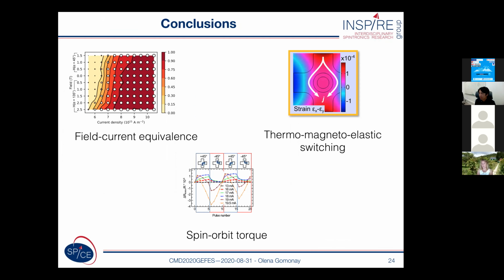With this, I'm at the end of my talk, and to conclude, we demonstrate that current induced switching can involve more mechanisms than we assumed before. The current in platinum creates not only direct spin orbit torques which can induce switching, but it also creates a very complicated system which involves magnetoelastic interactions. And this makes physics much more complicated, but opens a way to manipulate and optimize a switching by proper tailoring of the devices and electrodes.